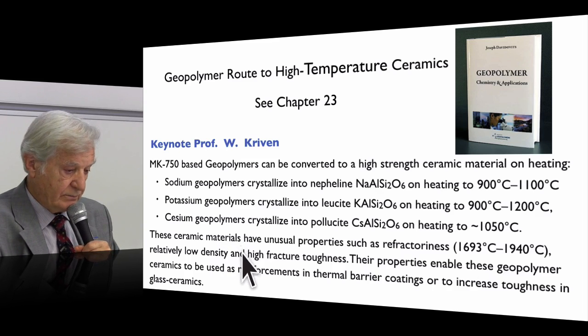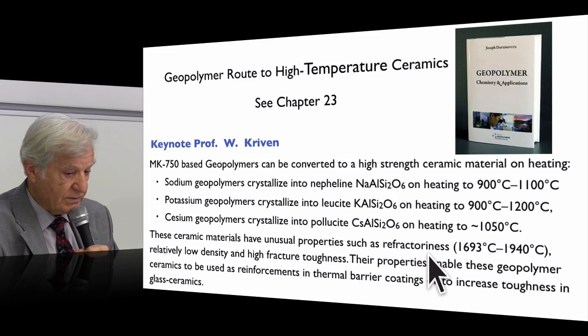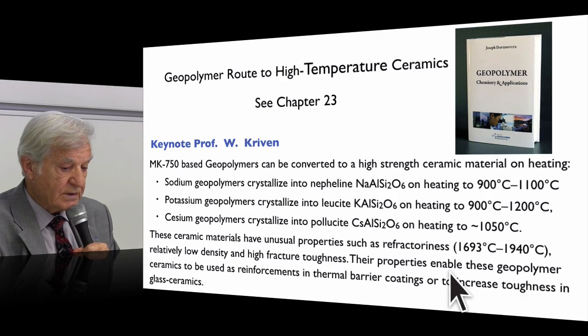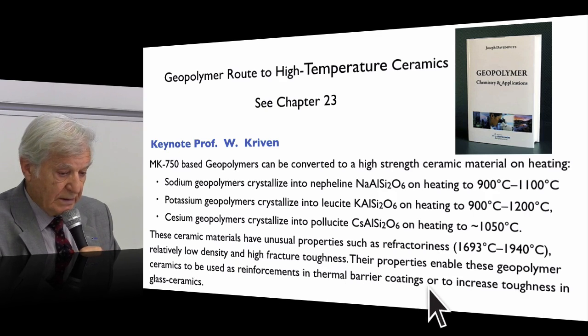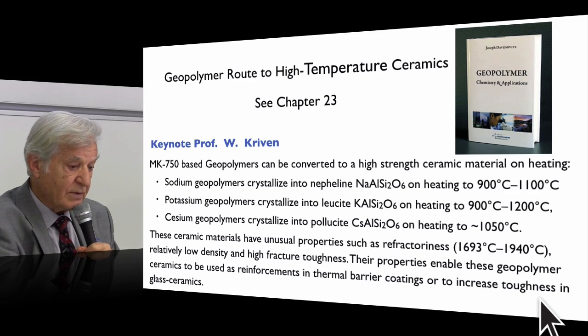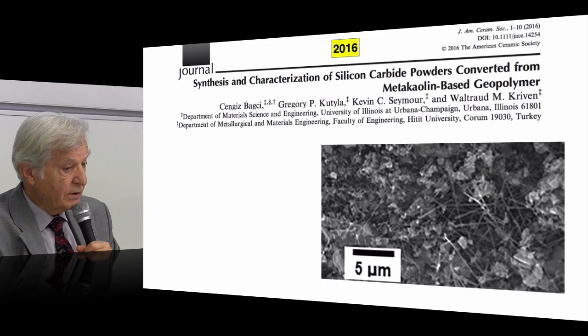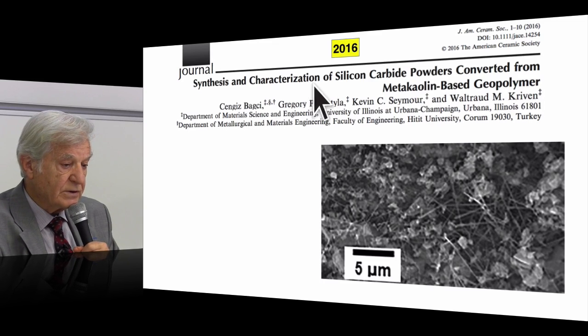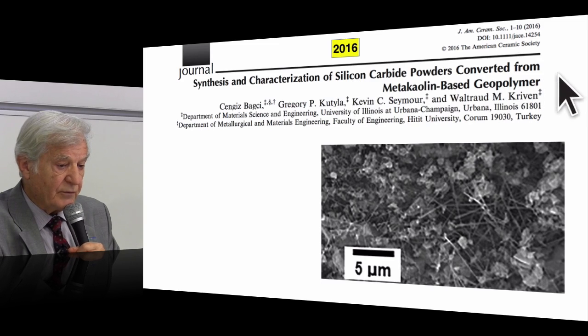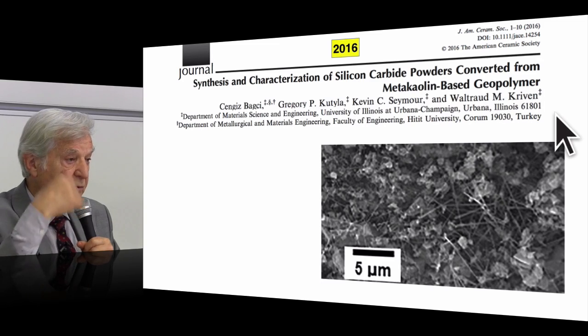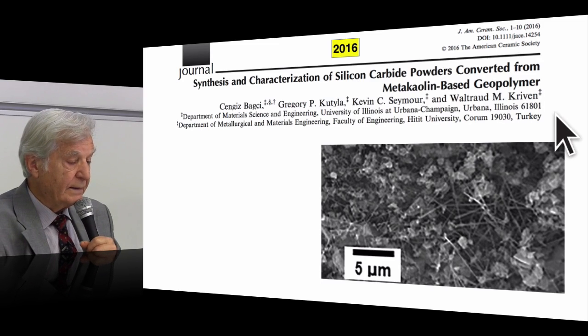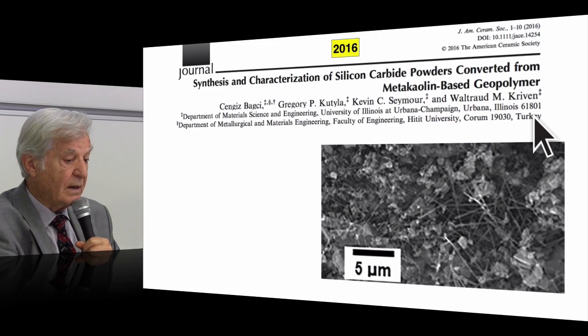These ceramic materials have unusual properties such as refractoriness, relatively low density, and high fracture toughness. Their properties enable geopolymer ceramics to be used as reinforcement in thermal barrier coatings or to increase toughness in glass ceramics. They continued with a very interesting study that was published in 2016, synthesis and characterization of silicon carbide powders converted from metakaolin-based geopolymer. So they are doing a geopolymer mix and are manufacturing silicon carbide in situ.